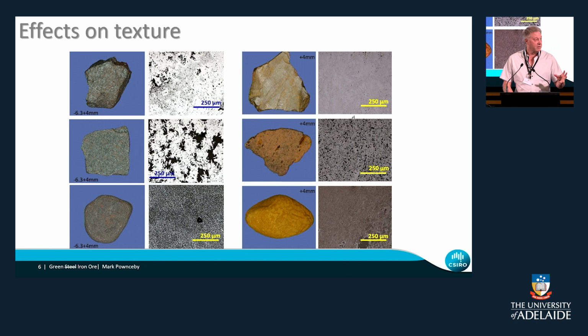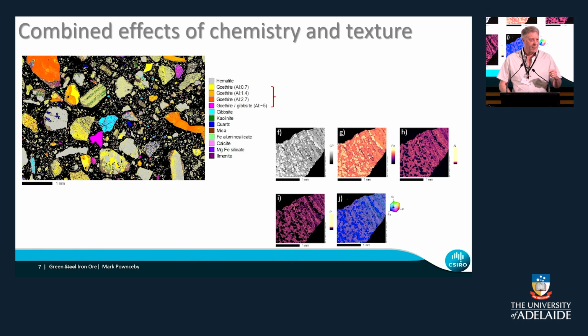On the right, we've got our other main component of Australian iron ores, which is goethite. And again, we get different textures in the goethite. We get really glassy looking goethite, which we call vitreous goethite, which is the top one, through to this thing which people sometimes call limonite or ochreous goethite, a really oxidised, impurity-laden material. Consequently also, there are effects on things like hardness. So our lump ores would be the high-grade, dense hematite ores or the denser goethite ores, whereas our fines are generated by the goethites and the really porous hematites.